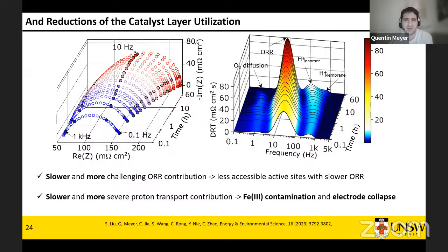So starting from the beginning, what's happening in the catalyst layer, and why do we have proton transport resistance in the ionomer? So there are two ways to look at it, and this gives us just ideas of what's happening, not the definite answer. First one is we have a lot of iron demetalation, and as ions saturate my ionomer, they will stop proton transport because they're just literally another ion that's stuck. The other reason is as the electrode is corroding on itself, the proton pathway becomes longer and longer and longer, much slower. That would explain why we see such a large proton transport in the ionomer phenomena.